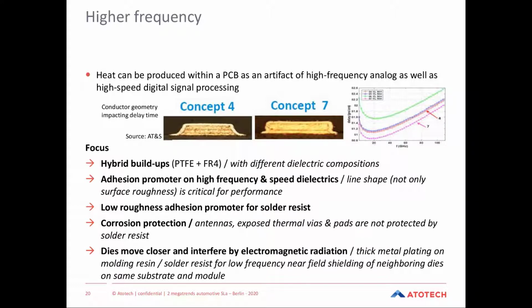Those low loss Dk Df dielectrics are more costly than standard FR4 materials. So those dielectrics are only being used on those layers where high-speed signals are being processed. This leads to hybrid buildups. One layer might be PTFE containing, whereas the other layers are FR4 for cost reasons. This challenges any kind of desmear, as a compromise between the different materials needs to be identified to desmear the PTFE containing or FR4 layers.